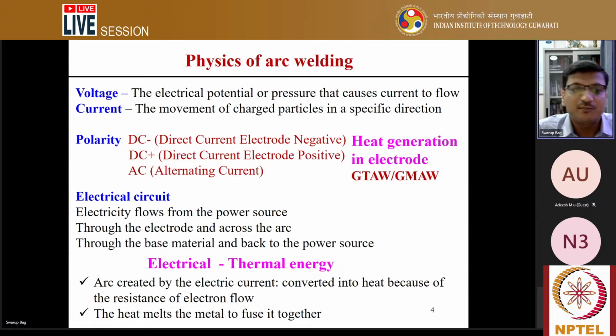But if you use AC current, that is an alternating current, there is a reversal of the heat generation between the workpiece and the electrode. Specifically, materials having high affinity to form oxides, for example aluminum, quickly form oxides, and it's very difficult to remove the oxides during the welding process. So in that case, the alternating current will be more usable, because almost 50% heating occurs at the workpiece, and then in the next cycle there is heating of the electrode.